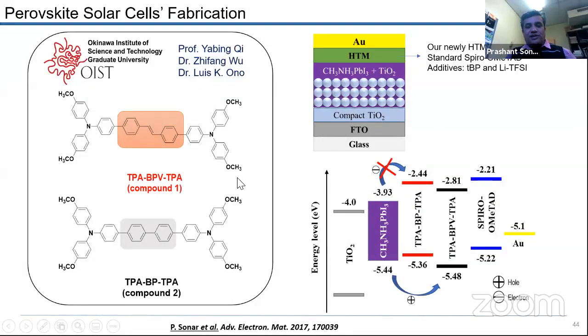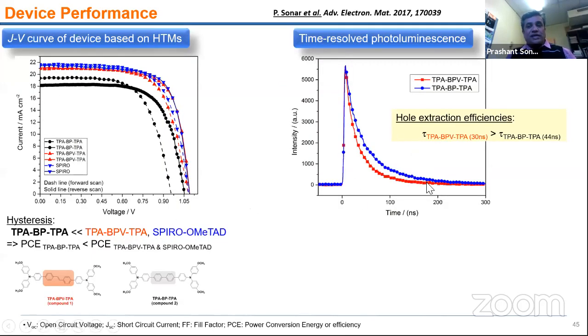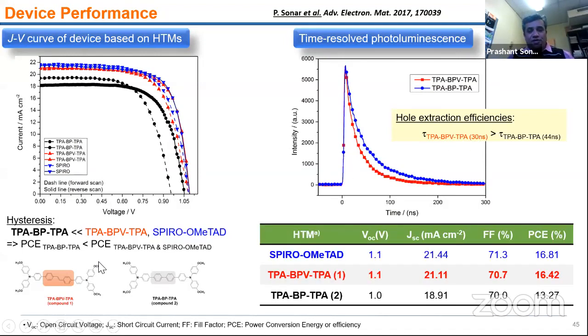Then looking at these two other molecules with phenylene vinylene phenylene and biphenylene, we did the similar hole extraction efficiency study using time resolved photoluminescence, where we can see in the case of TPA-BPV-TPA it is 30 nanoseconds, whereas TPA-biphenyl-TPA is 44 nanoseconds. It means that the BPV molecule has a higher hole extraction ability, so it might be the better material compared to the BP. And indeed, BPV has shown an efficiency of 16.42, whereas BP has shown 13.27. Based on this hole extraction data, this clearly indicates that BPV has a better ability.